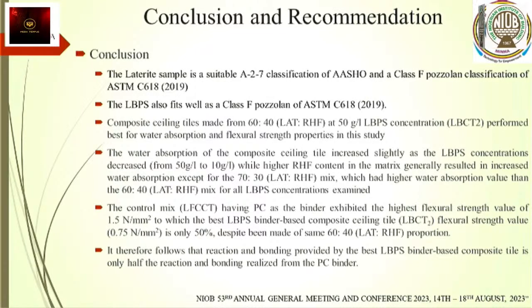The LBPS is also class F pozzolan, and we discovered that 60-40 laterite RHF at 50 grams per liter was the best performed of the ceiling samples using LBPS. But we observed that the water absorption also shows that same sample as the best performed for when we are using laterite and RHF with the LBPS as the binder. But we observed that it was just half of the flexural strength that the control gave. So we believe it can still be improved upon.